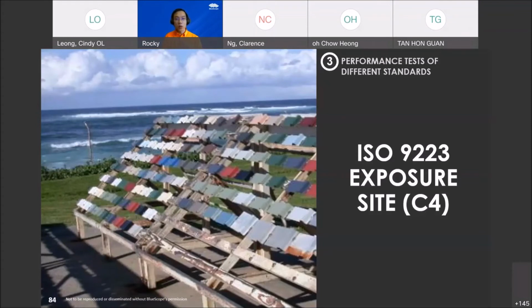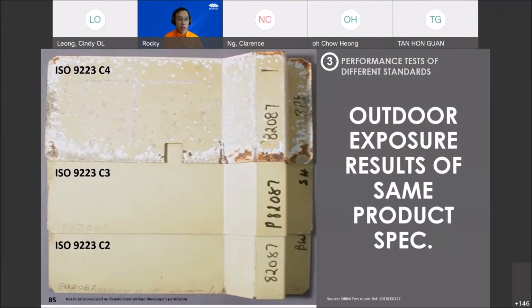And the reason why they have all these testing sites is because it will actually yield much more severe results if it's placed in C4. So for example, these three samples are actually the same product spec, the same product, but they were cut into different parts and placed in different environments. And when it's time to judge, you can see that the product placed in C4 started corroding. So it means it is not suitable to be used for C4 based on the test duration. C3, C2 might still be possible.